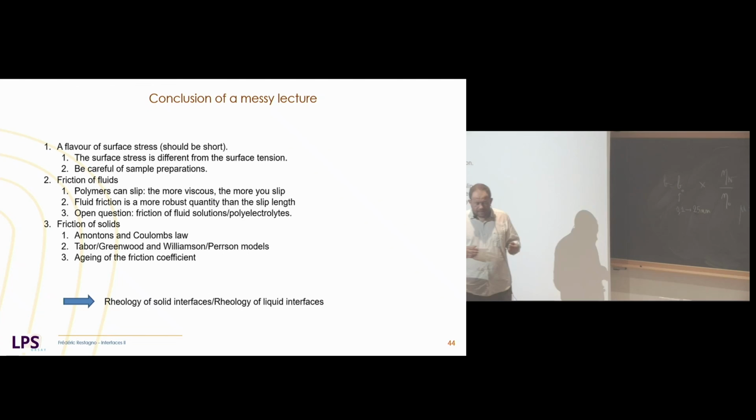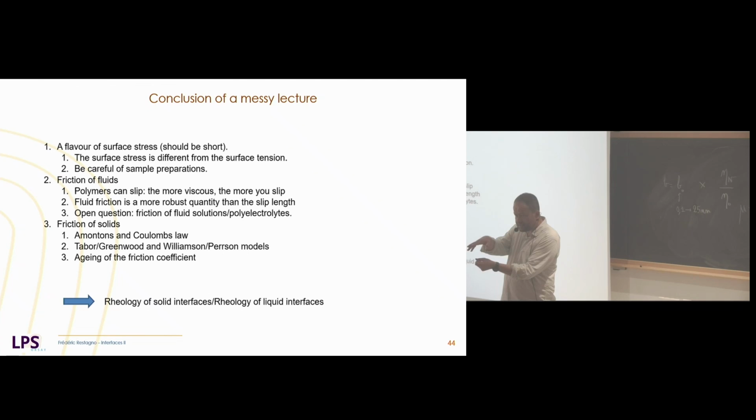The idea is that you have these asperities in contact. You plastify them when you make the contact, and then you have to destroy them. And when you destroy them, then you pass the peak of static friction. But as soon as you move your surface, you make new contacts, and then you have to kill new contacts every time, which means that there is still a dynamic friction coefficient. Yeah, I would say that, but there is also an effect of the velocity on the creep of your materials that you have to take into account if you want to make a whole description of these effects of velocity. I mean, it's not just the yield stress of the material.